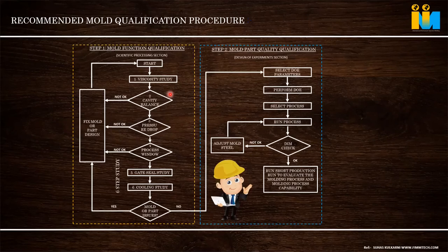At 6 seconds, if a sink mark or defect is coming on the part, it means our gate is undersized. We have to improve the gate size. A small change in the gate can give a drastic difference. The shape of the gate is also important. Better the volume, even if the opening may be small, like we have discussed with a high volume submarine gate, that gives a better result.